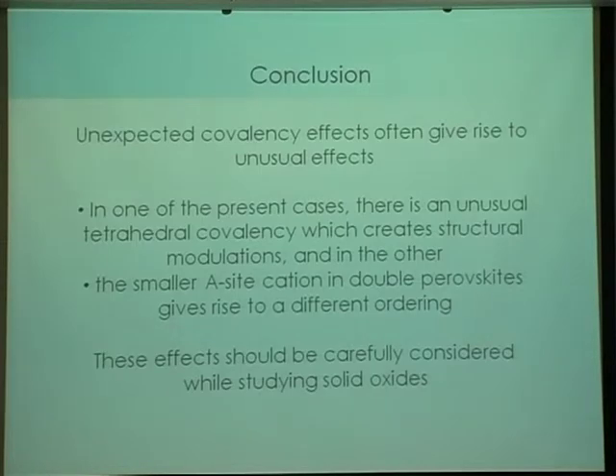I don't have time, so the conclusion is I have shown you two different cases where a tetrahedral covalency created strange structural modulations. In another case, the smaller A-site cation in double perovskite gave a different kind of ordering. So the point that I tried to establish here is that this metal-oxygen covalent linkage in these oxides often does strange things, and unless you are aware of it, you ought to get into a wrong conclusion.